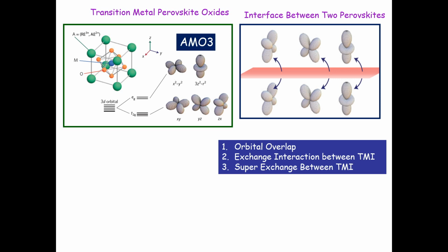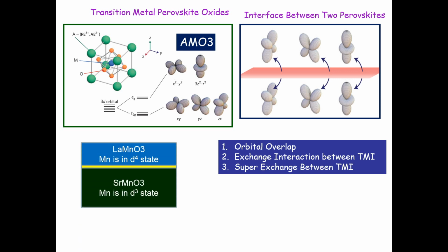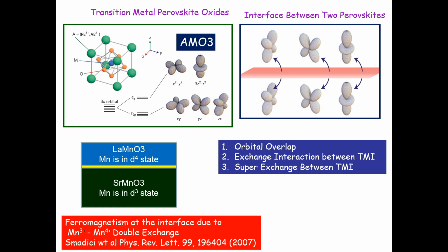I'll give you one very good example of this super exchange. If I take strontium manganese oxide, which is an antiferromagnetic insulator, and lanthanum manganese oxide, that is also an antiferromagnetic insulator, but here manganese is in D4 state, here manganese is in D3 state. These two can talk to each other via transfer of an electron via oxygen. And that double exchange, a form of super exchange, makes this interface metallic and also ferromagnetic. So you have a two-dimensional metal which is ferromagnetic. And this was established beautifully by this group at Argonne National Laboratory about 7-8 years ago.